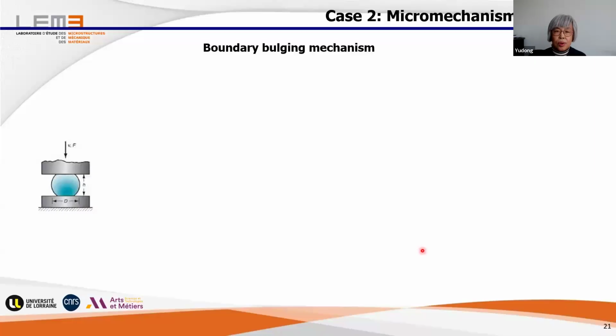This allows us to go a little bit deeper to see how such a bulge happens. This is a compression, exactly our case. When this dimension decreases, this dimension expands, and so in this direction the material experiences a kind of tension. We can consider we have two grains here, grain 1 and 2, with this extension in this direction. At such high temperature, the boundary is very weak, and so the boundary becomes broadened.